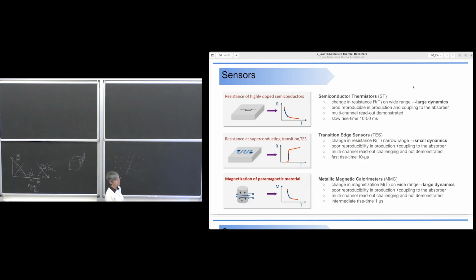But they are slow. So the rise time is between 10 and 50 milliseconds. Then we have transition edge sensors that are based on superconductors. So this is an answer for your question. In correspondence to the critical temperature, they have a step increase in the resistance. And you can produce the film with different alloys, and you may be able to tune the position in temperature of this transition.